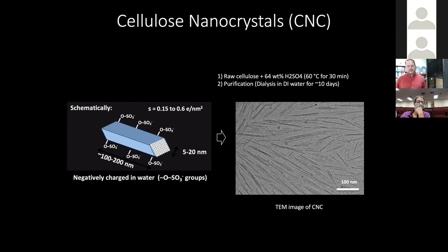Yeah, it depends on what you look at. In terms of bleaching, it's much better because, not being a chemical process, it doesn't degrade. The cellulose has a really low absorption in the UV, so also in terms of UV stability, it's good. Once you remove the sulfate ester group, for example with a basic treatment post-assembly or a slight heat treatment, you might modify the crystalline structure a little bit, but you can also make the structure somehow hydrophobic so that it can be, to a certain extent, water resistant too.